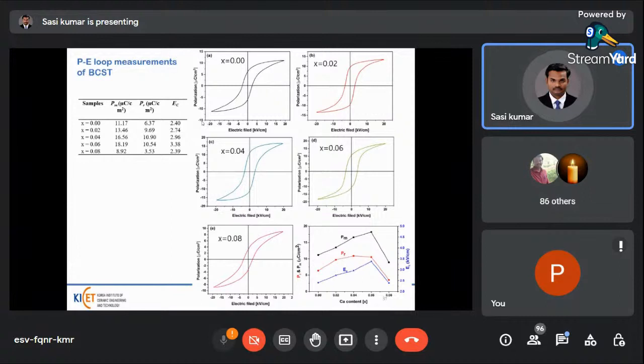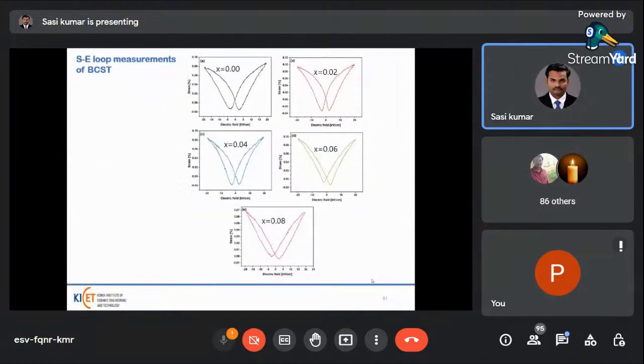And then PE loop measurements of BCST. So polarization versus electric field plots are measured for different compositions, and the variation of this composition is mentioned here. The maximum polarization, Pr and P max, and the higher value of coercive field are obtained for x equal to 0.06 composition. This may be due to the composition being nearer to the morphotropic phase boundary of these compositions. And then SE loop, strain versus electric field measurements of BCST ceramics, is mentioned for different compositions.